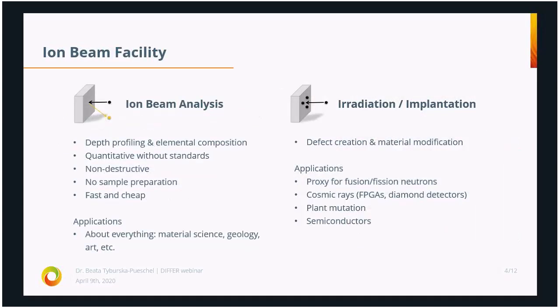As I said, we can perform ion beam analysis and ion irradiation. For the ion beam analysis, you use it if you want to measure the elemental composition of your sample and perform some depth profiling. This method is quantitative without standards. With our current error bars are about 5%, but we could tweak it down to 1%. It is a non-destructive method.